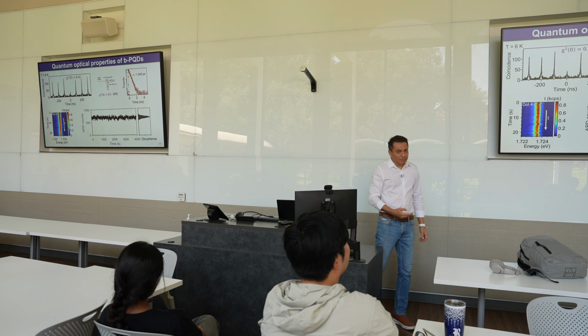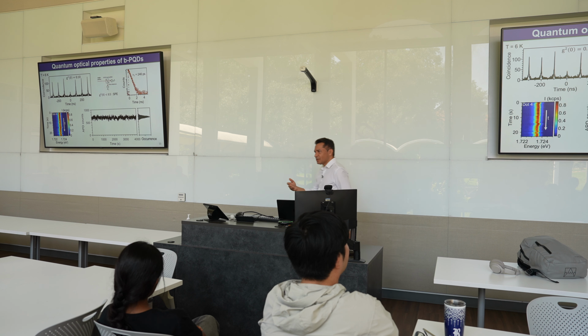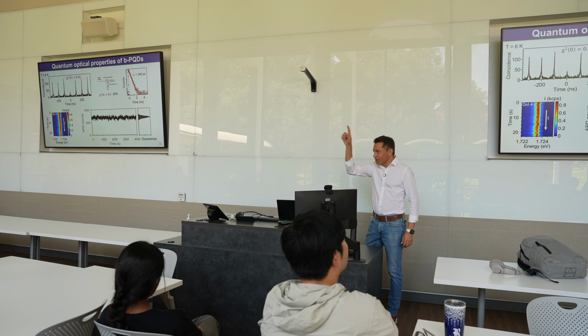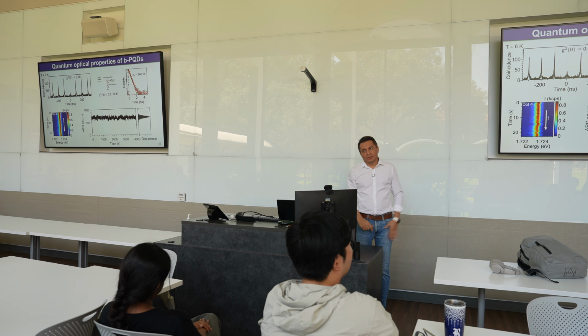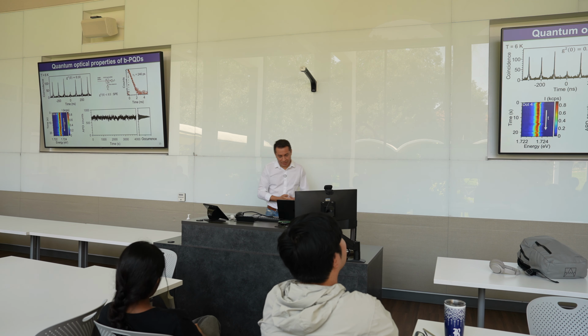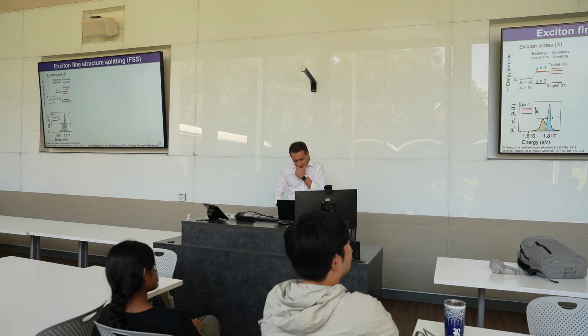And there is something called the coherence lifetime. Do you guys know what the coherence lifetime is? We talked about this purity of the photon and things like this. You want that to be equal to this lifetime, which means that as long as my electron-hole pair, my exciton, is really living, I can do computation there. So that's the best I can do. We get something on the order of T1 by T2, a coherence lifetime of about 200 picoseconds. That's really, really long for this. So that's kind of where we are.